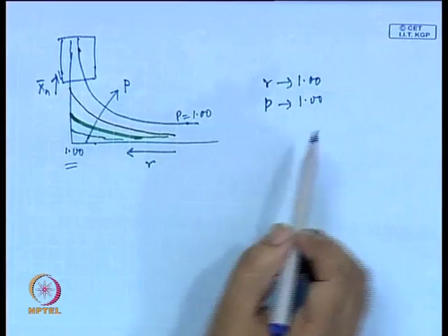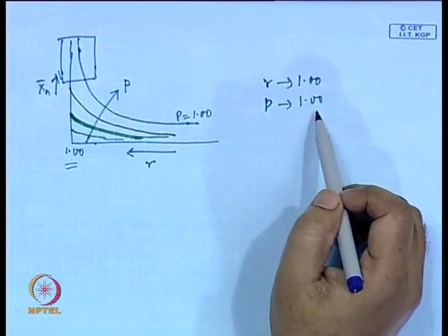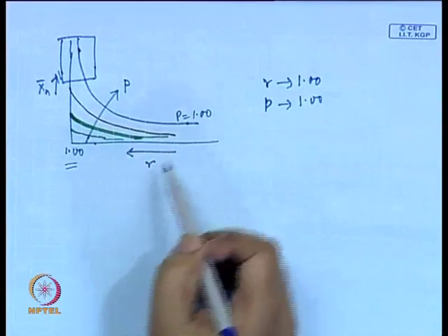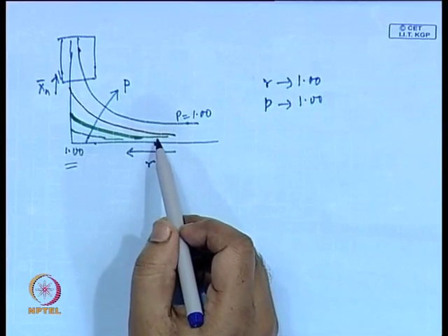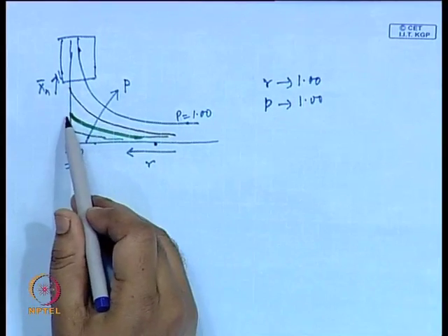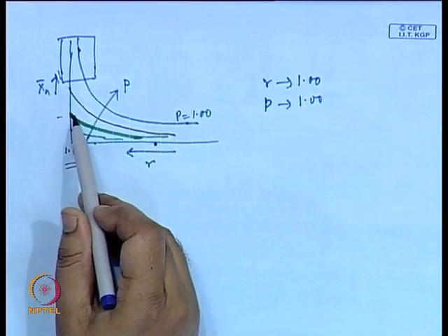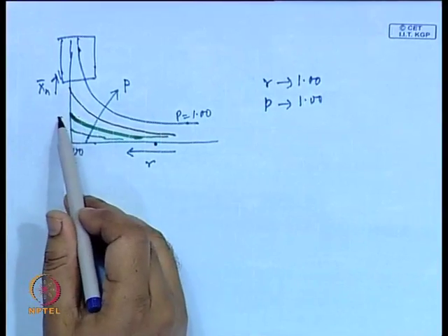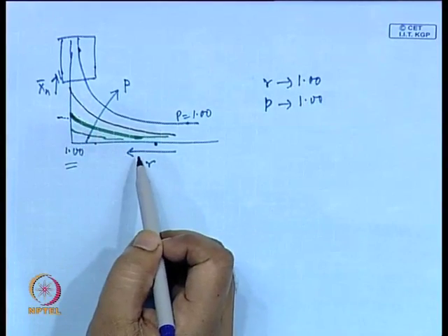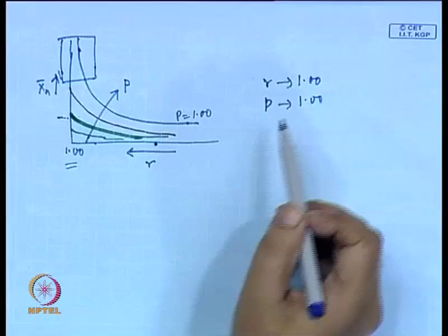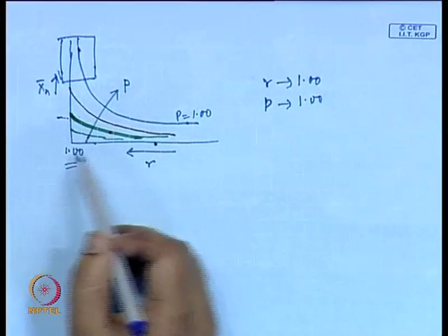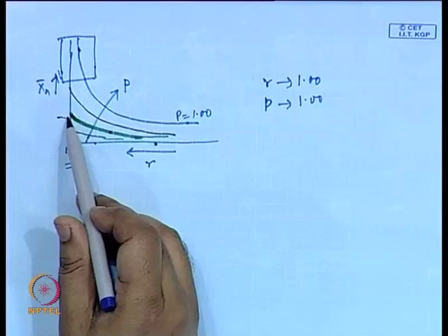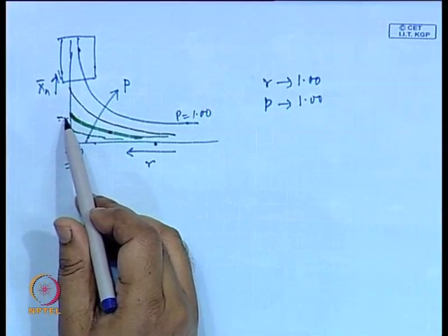If you are off in either of these two factors, if your R is somewhere here, then no matter what your conversion level is, you cannot reach high molecular weight, you will stop here. Same if your P is low, like this curve, no matter what your R is, you can only reach up to this level.